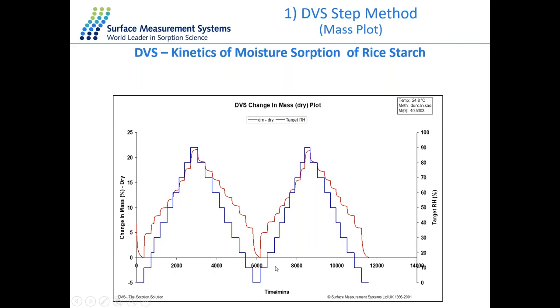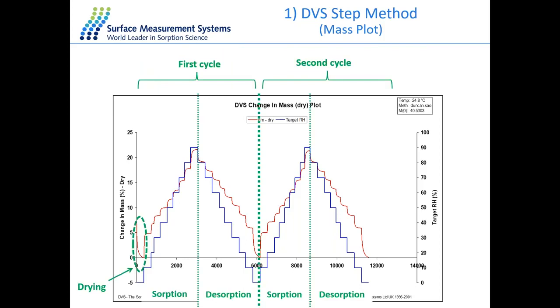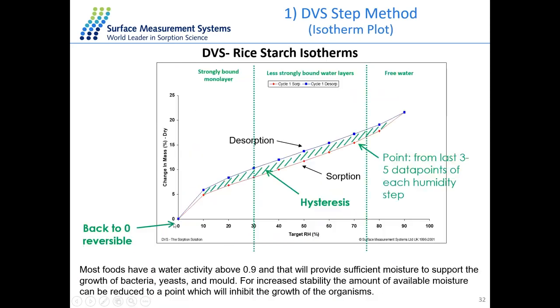So in this case, we can see that it's a reversible experiment. Just to clarify, this is cycle 1 and the second cycle, and this at the beginning is our drying stage. We can also plot an isotherm.